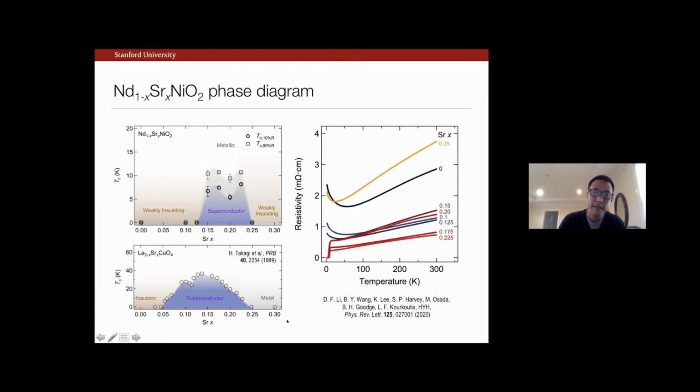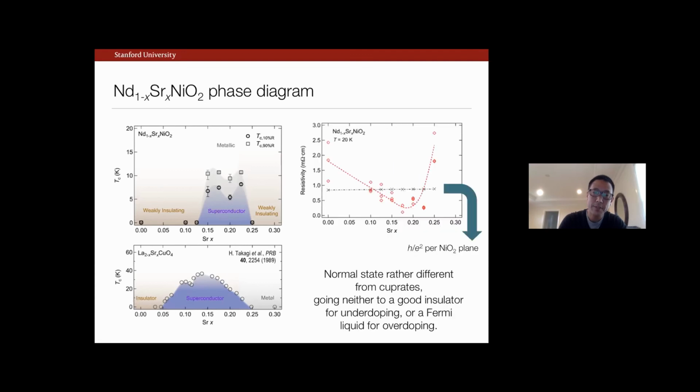And if I take, for example, another picture of this variation, nominally using the low temperature resistivity just above Tc as a scale, here it also gives you this scatter I show you because of these extended defects sample to sample. But nevertheless, the trend is clear. There's a minimum associated with this region of superconductivity.